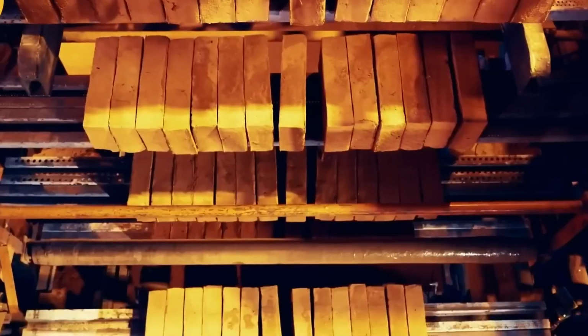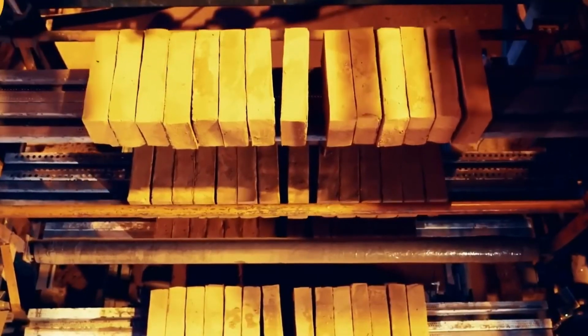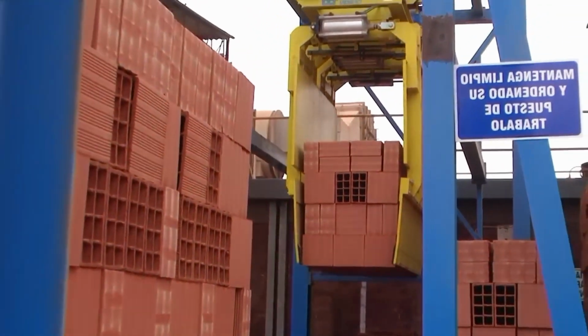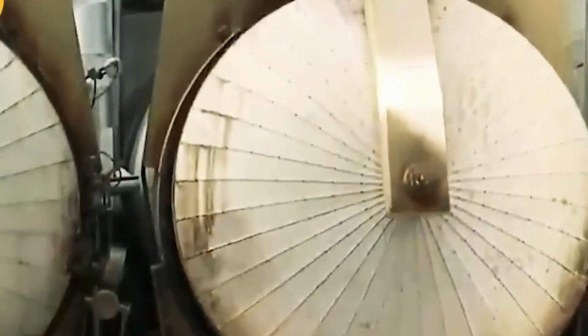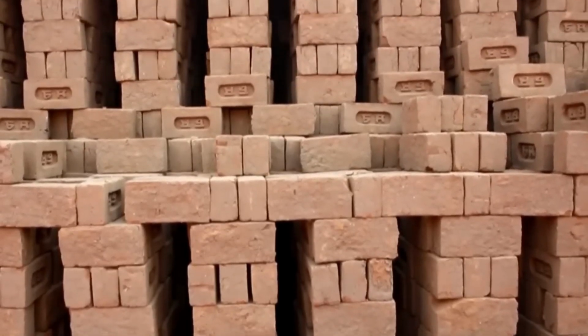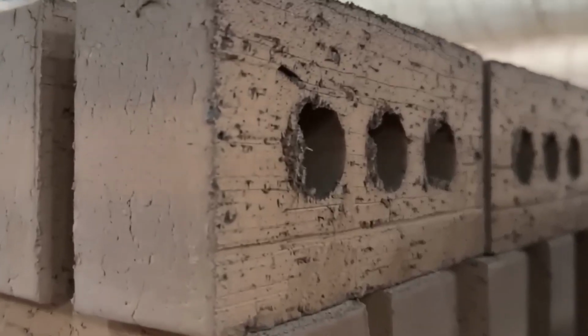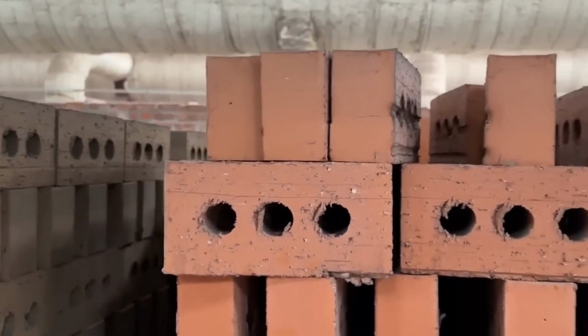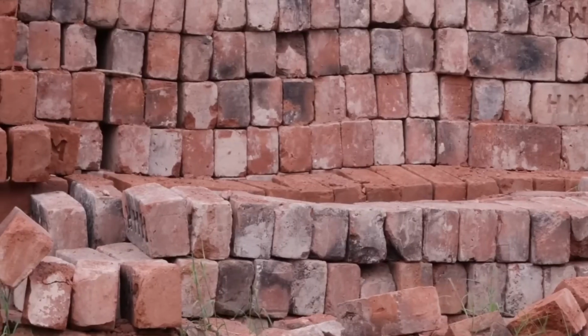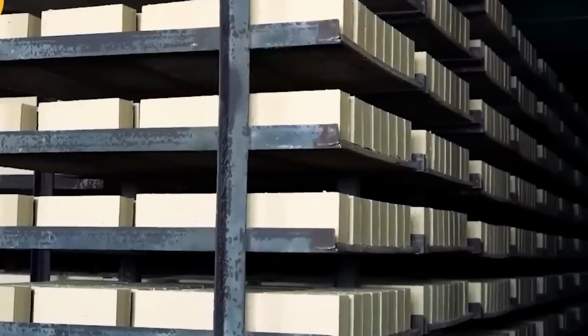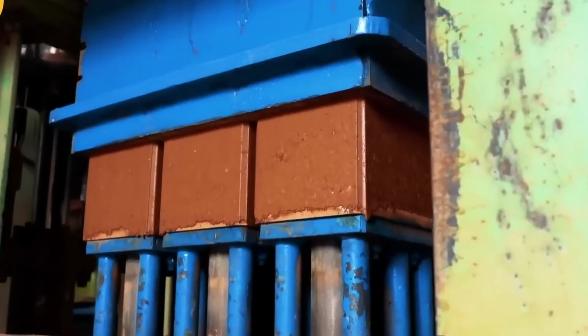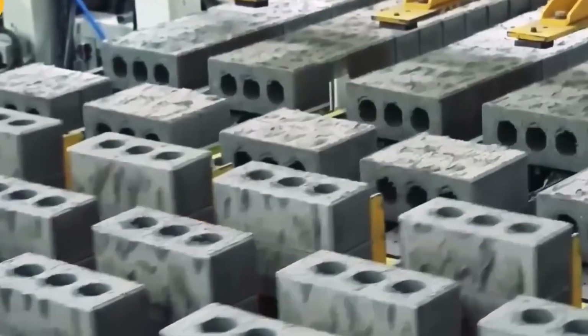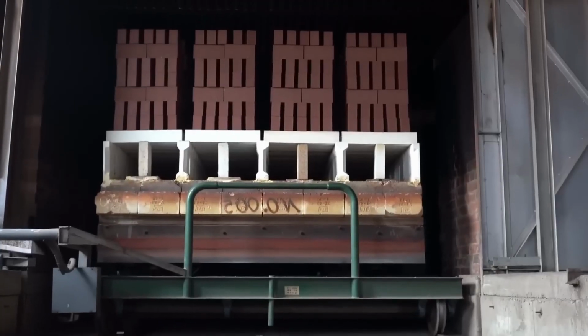After the firing zone, the cooling process begins. This phase must also be gradual. A brick that emerges from over 1,000 degrees Celsius and cools suddenly can crack due to thermal stress. The surface and the interior contract at different rates, causing fractures. Therefore, the kiln includes a zone where the heat is reduced in a controlled manner. The air that cools the bricks heats up as it passes through them, and many factories reuse this hot air to supply the drying chamber or preheat the initial zone of the kiln. This recovers energy and reduces overall consumption. When the wagons leave the kiln, the bricks are already fired. Their color is final, their structure is stable.